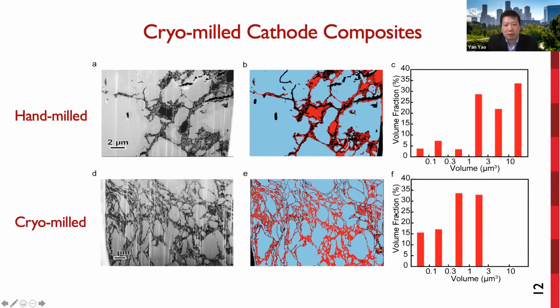To further improve material utilization, we look into optimizing the microstructure of the electrode. In contrast to NMC particles, which have uniform shape and size, organics typically have a wide distribution of shape and size, making it very difficult to engineer the microstructure. We discovered that a cryo-milling process can greatly reduce the PTO domain size. From the cross-section SEM images, the black phase is PTO with carbon, and the white phase is the solid electrolyte phase. We therefore segmented the SEM images based on grayscale. We see the size of PTO domains for cryo-milled samples is about a factor of 10 smaller than hand-milled ones.